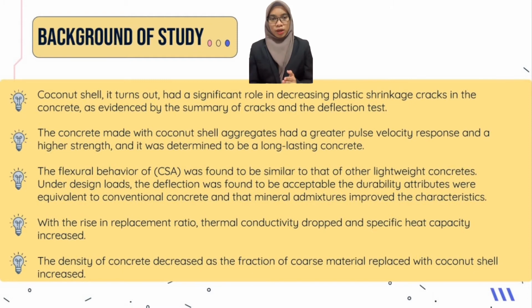The concrete made with coconut shell aggregates had a greater pulse velocity and a higher strength, and it was determined to be a long-lasting concrete. The flexural behavior of CSA was found to be similar to that of other lightweight concretes. Under design loads, the deflection was found to be acceptable. The durability attributes were equivalent to conventional concrete, and mineral admixtures improved the characteristics. With the rise in replacement ratio, thermal conductivity dropped and specific heat capacity increased. The density of concrete decreased as the fraction of coarse material replaced with coconut shell increased.